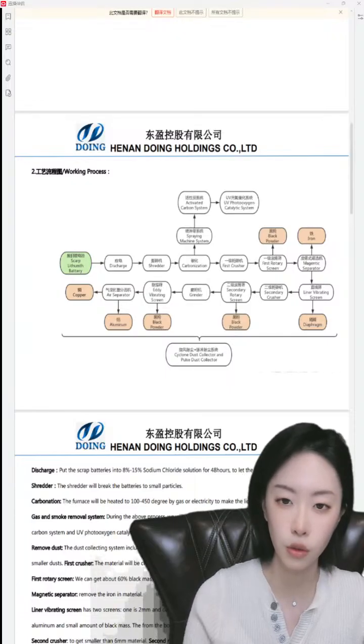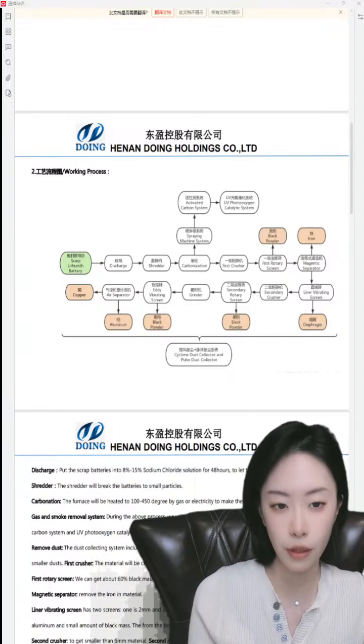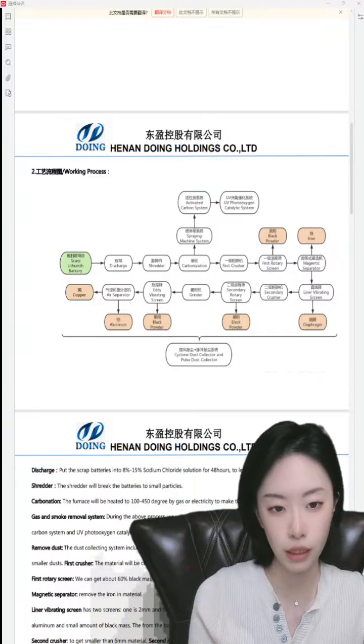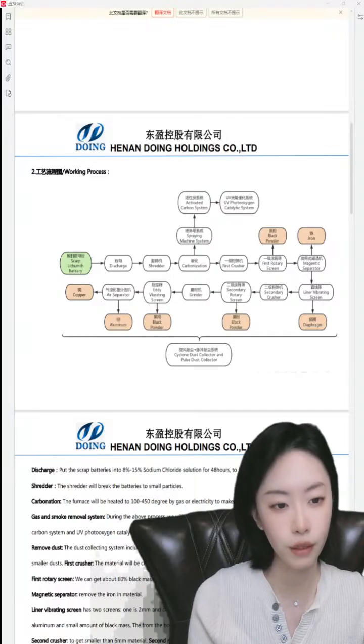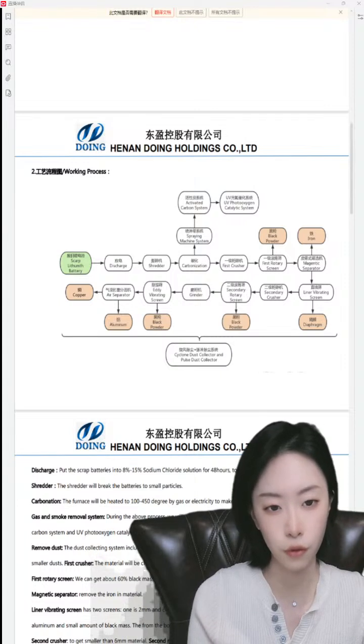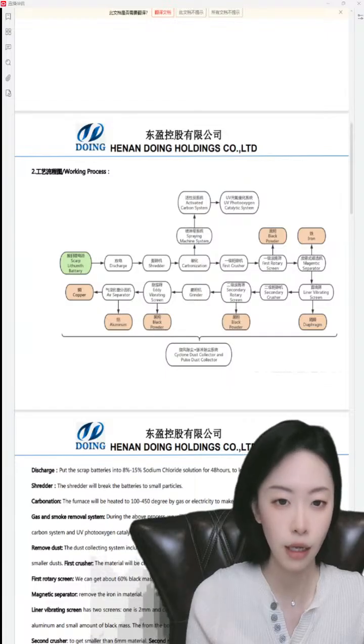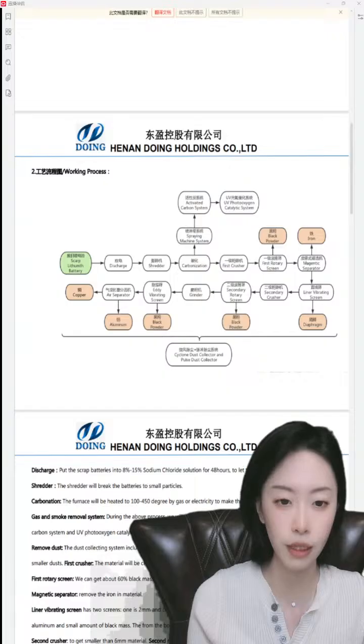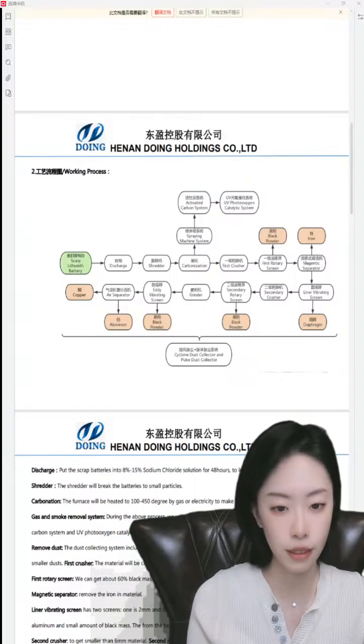We need to put the scrap lithium battery into a sodium chloride solution with a concentration of 8% to 15% for nearly 2 days, so that the positive and negative terminals of the battery short circuit to let the battery discharge completely. This is the first step.